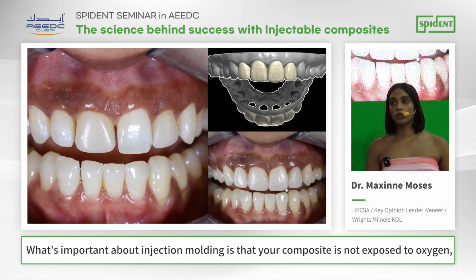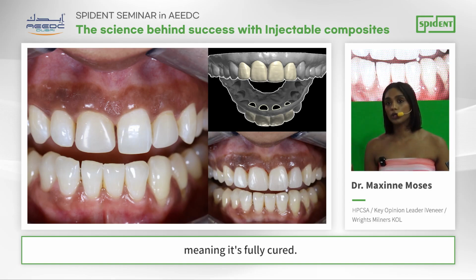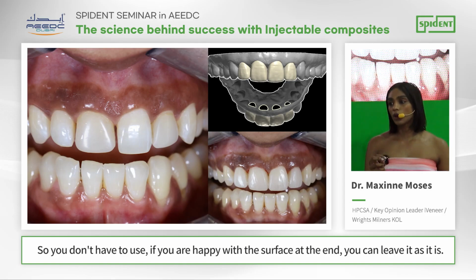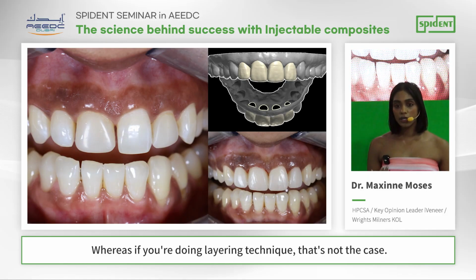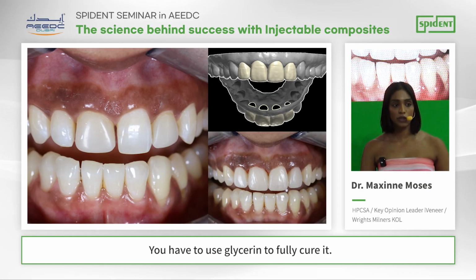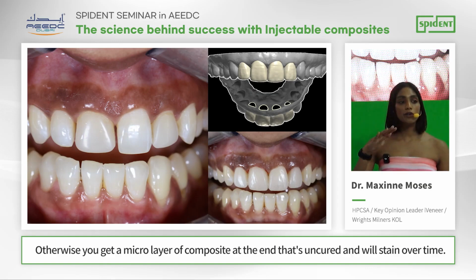What's important about injection molding is that your composite is not exposed to oxygen, meaning it's fully cured. So if you are happy with the surface at the end, you can leave it as it is. Whereas if you're doing layering technique, that's not the case. You have to use glycerin to fully cure it. Otherwise, you get a micro layer of composite at the end that's uncured and will stain over time.